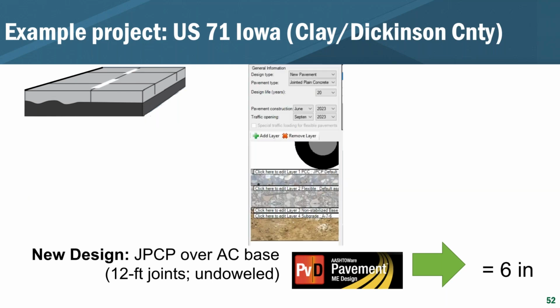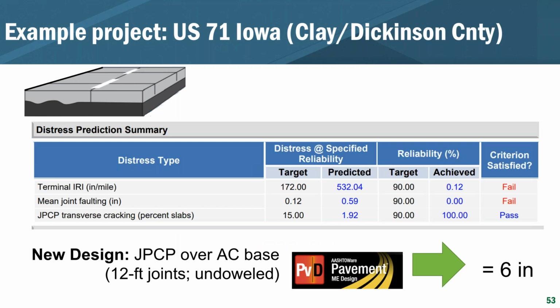So here I do a new design with a concrete pavement, a jointed plain concrete pavement on top of an asphalt base. And I still use the 12-foot joints undoweled. If I threw in a dowel, of course, that would disappear. So I'm not really concerned about that. And also I use the most erodible layer, and your faulting is extremely sensitive to the erodibility of that layer. So I'm not too concerned about that. But then when I do the 6-inch overlay with the new concrete, I go from 13 to about 2% fatigue cracking.